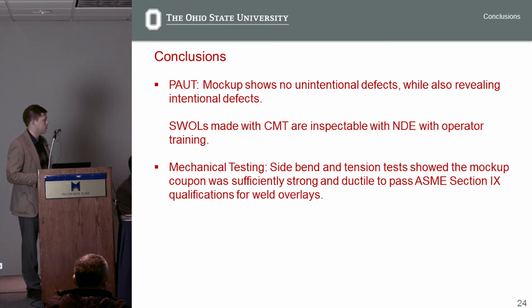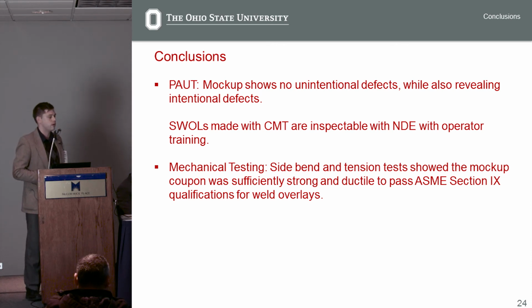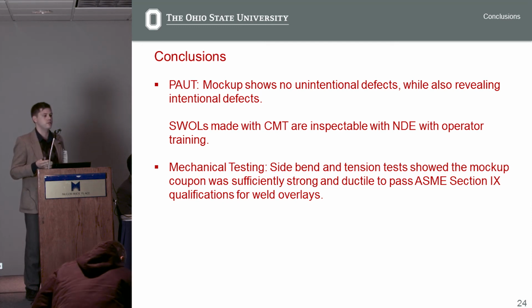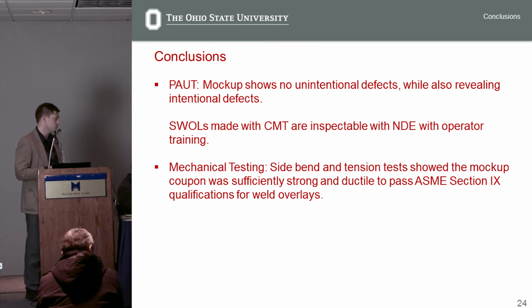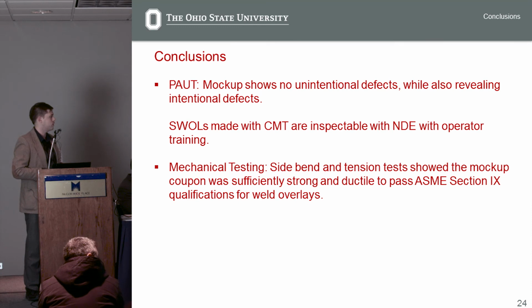So the conclusions are the results of the experiments. The phased array ultrasonic testing showed that mock-ups show no unintentional defects while also revealing intentional defects, which means that structural weld overlays made with CMT are inspectable with NDE methods with operator training, provided that they know what CMT does to a microstructure. And mechanical testing, side bend and tension tests showed that the mock-up coupon was sufficiently strong and ductile to pass ASME Section 9 qualifications for weld overlays.